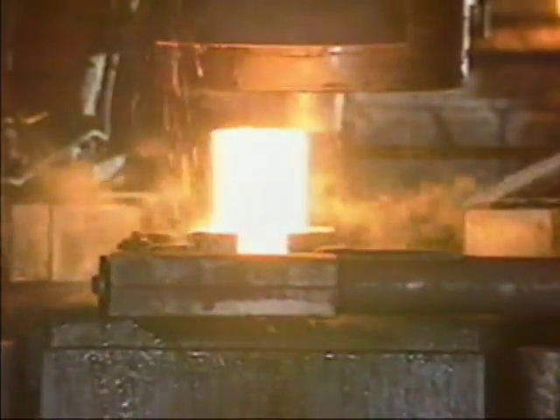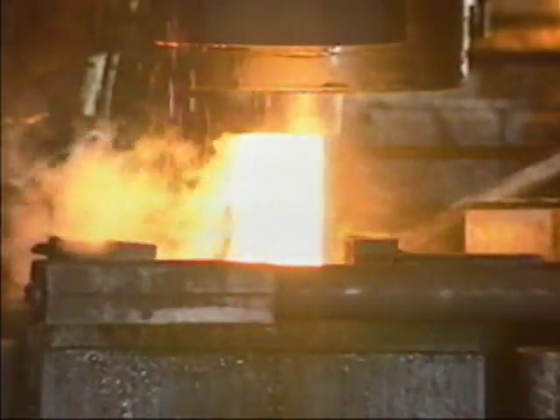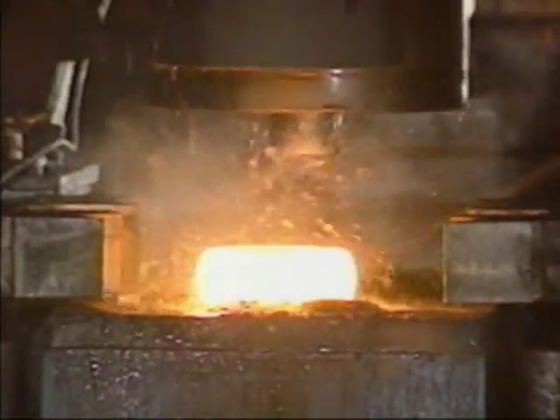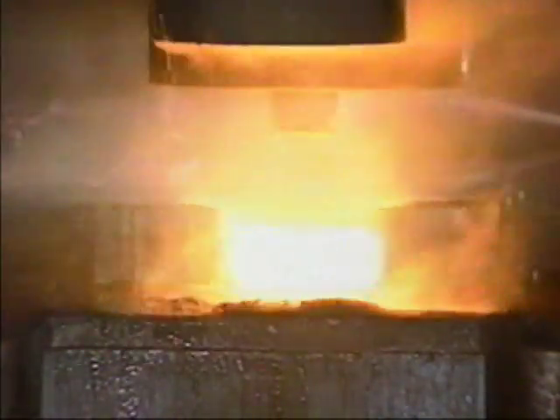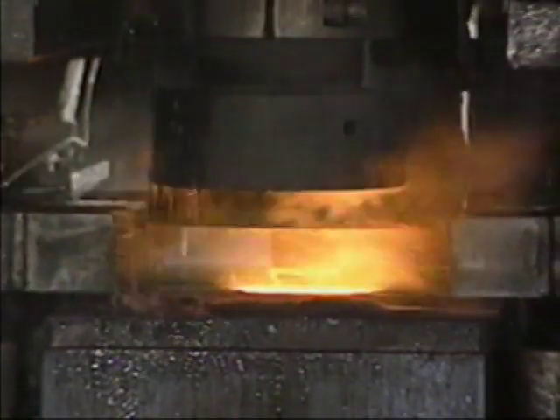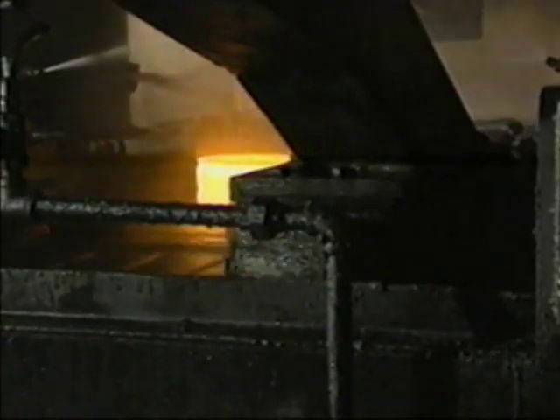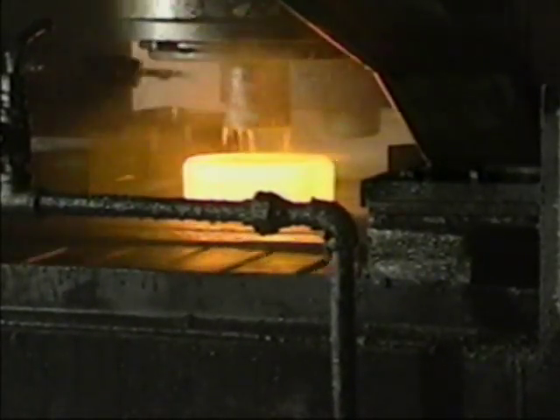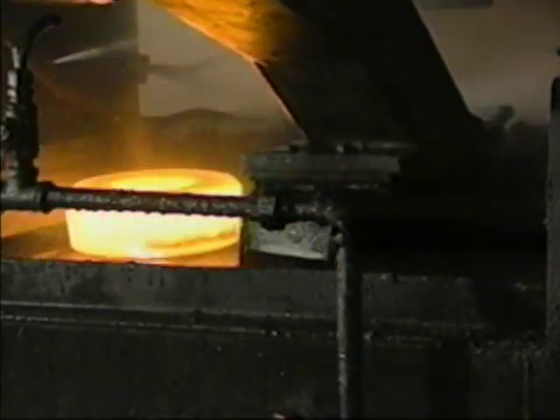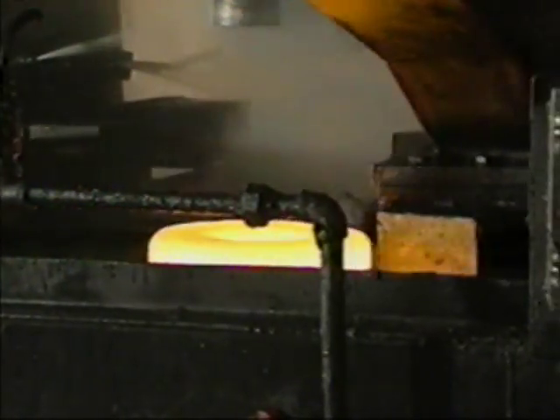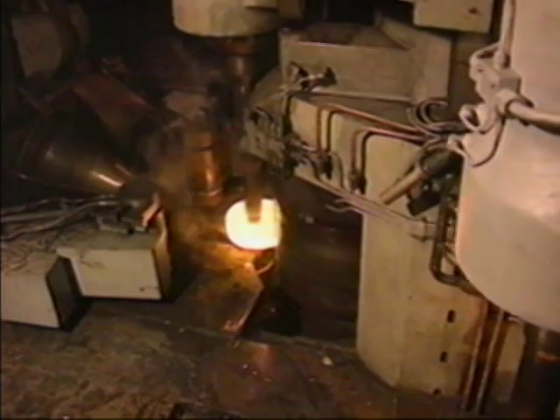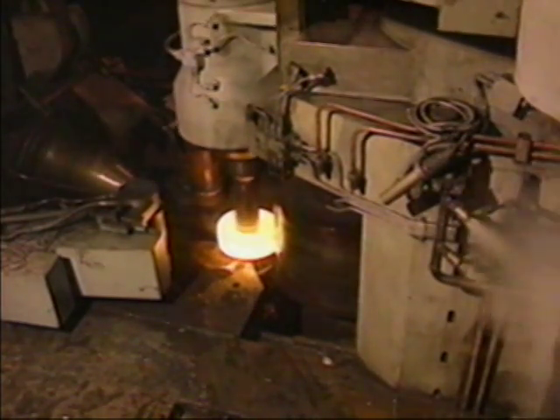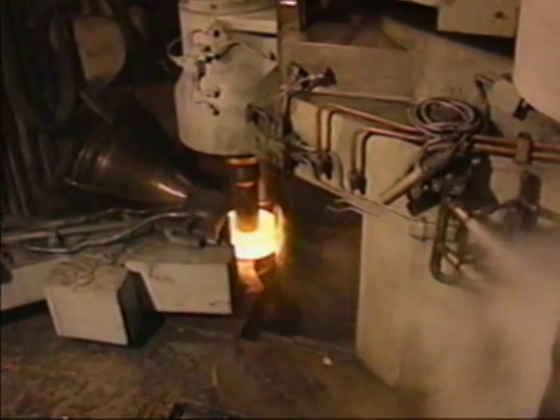A robotic swivel manipulator quickly grabs the hot block and feeds it to an automatic 1,000-ton blanking press, which upsets, indents, and pierces the blank. A conveyor carries the blank to an automatic 40-ton radial, 25-ton axial ring mill, where it is rolled to size in much the same manner as on the large ring mill.